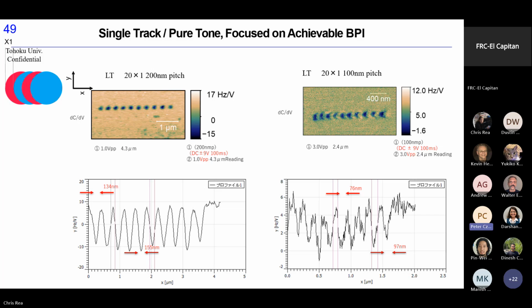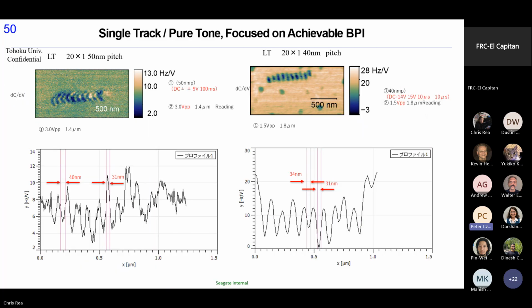At first, we write a single track, singlet reversal pattern. The first pitch selected, the left one, is 200 nanometer, but in this case, not a single domain. Then we reduced the pitch to 100 nanometer, the right case. In this case, you can see the single domain pattern, and the bottom one is a line profile of this image.